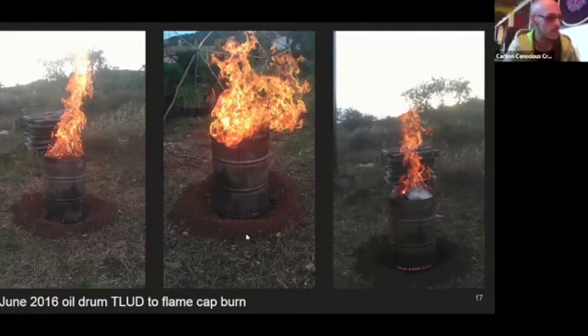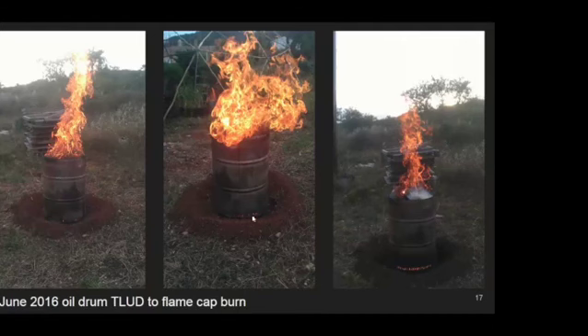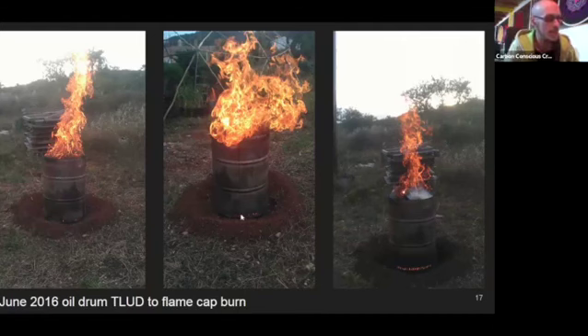Exactly. But you have to have the primary air holes open at the beginning, because if a flame cap kiln has vertical sides, then there's just not enough oxygen reaching the actual fire for it to properly carbonize. So it really helps to have those air holes, unless you can start higher up with the fire, then that would also work. So I saw Brian put a post with a metal grate in the bottom. And I guess that also is a way to make sure that there's still enough oxygen at the beginning stage of the fire. Because if you would try and light a fire on the bottom of a barrel, it gets a bit more difficult.